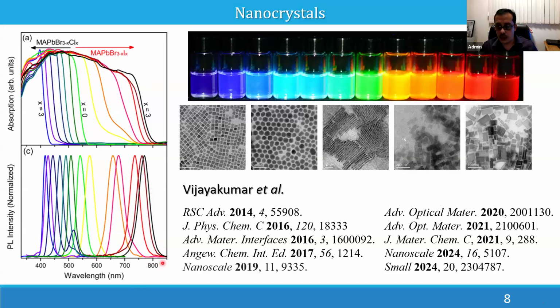That is the NIR window. So it can easily go to the NIR region by simply changing the halide ion from chloride to bromide to iodide. You can easily change the absorption. That is, absorption is shown here, and the emission properties, and it can be visually detected from the violetish blue